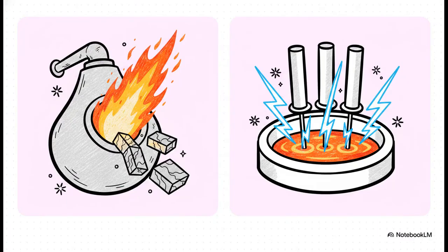To turn that concentrated iron ore into usable metal, it's typically shipped across the ocean to integrated plants and melted inside towering blast furnaces to create pig iron. Now, pig iron is packed with 3 to 4% carbon, making it way too brittle to be a fastener. Historically, we refine that pig iron into high-strength steel using a basic oxygen furnace. Here, a lance injects high-purity oxygen at supersonic speeds to literally burn off the excess carbon. The chemical reactions are so wildly exothermic, meaning they create so much heat that solid scrap steel has to be dumped in just to absorb the excess energy.